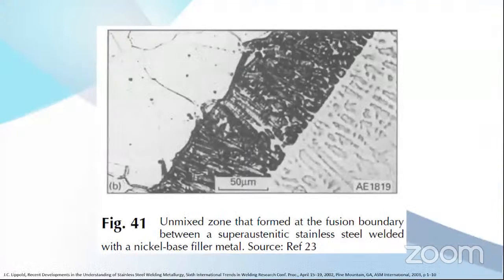And this is the unmixed zone that I mentioned before. Why is this a concern? Because this is the area, it doesn't always happen, but if it happens, this is the area that will have very low corrosion resistance, because it doesn't have the mixing from the filler metal, and it is rapidly cooled. You can see that this is black. It means that this is preferentially attacked by the chemical. This is the weldment, the fusion zone. This is the base metal. So you can see that this is rapidly attacked, but the others are still okay.